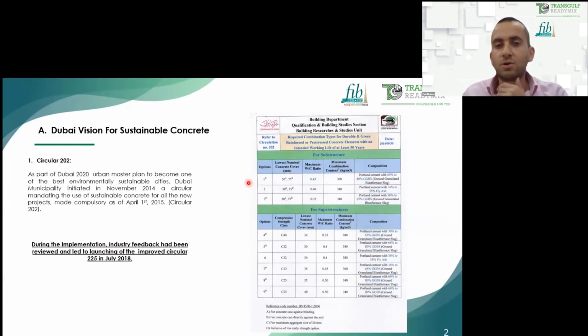In this circular, you can see that the concrete mixes are classified into 2 categories. The first one is for substructure mixes. It did not specify any concrete grades. It specified the minimum combination or minimum cement content, maximum water cement ratio, and composition. In all the options we have here, even for superstructure or substructure, the use of supplementary cementitious material is a must.